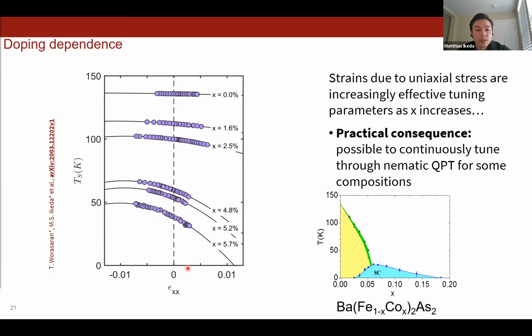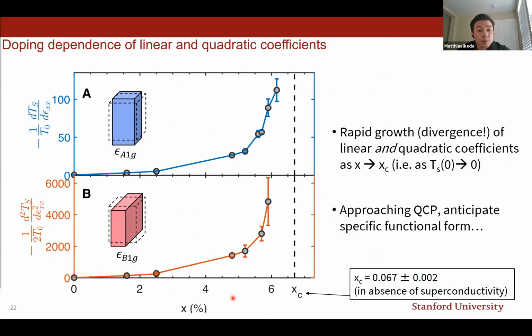And as a first practical consequence, we find that for the highest dopings studied here, it is possible to tune the nematic transition temperature continuously towards a quantum phase transition, or even through a quantum phase transition with strains that are technically feasible in our laboratory. Let me now show the linear as well as the nonlinear coefficient of the strain response of the nematic transition temperature as a function of cobalt concentration.